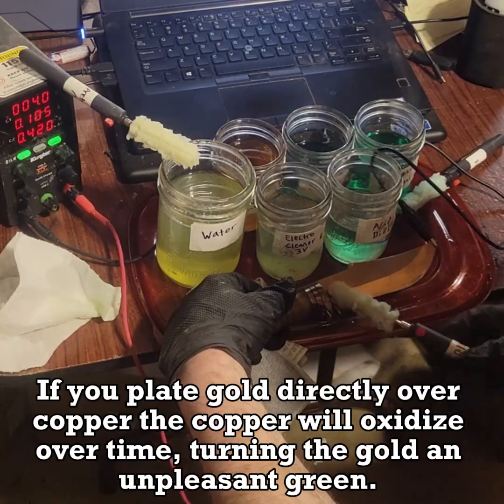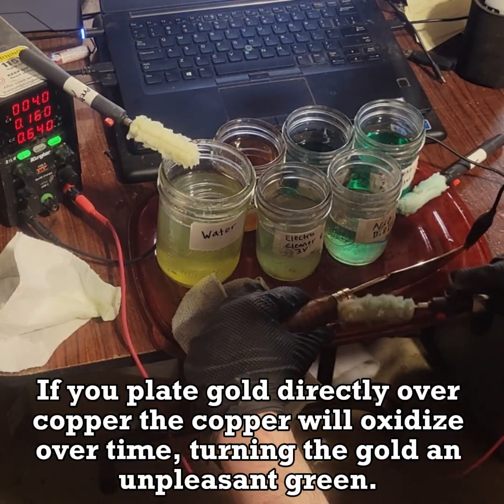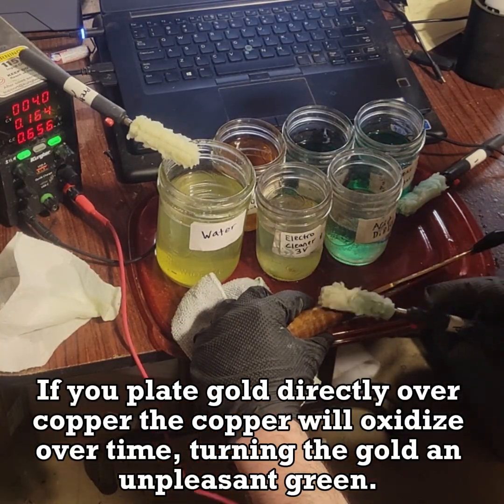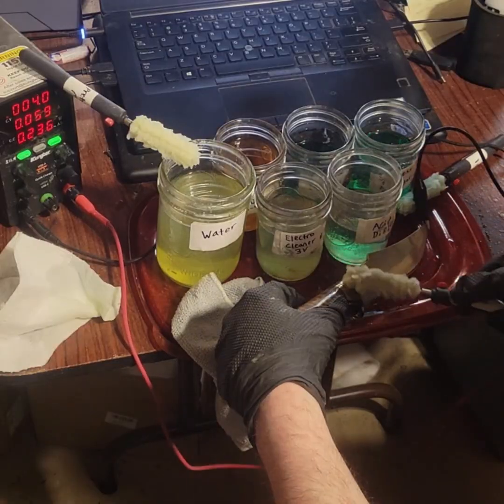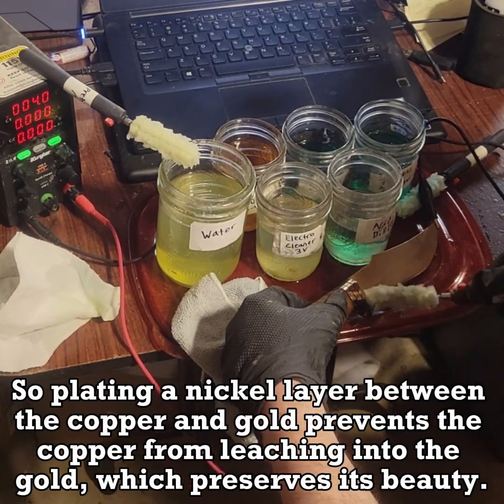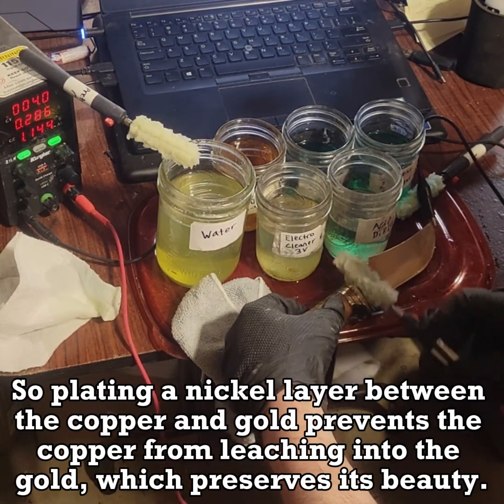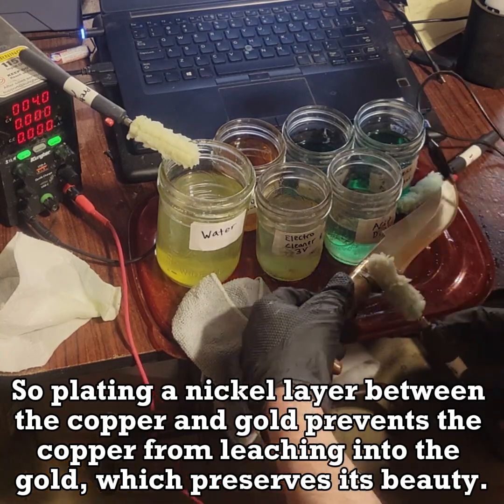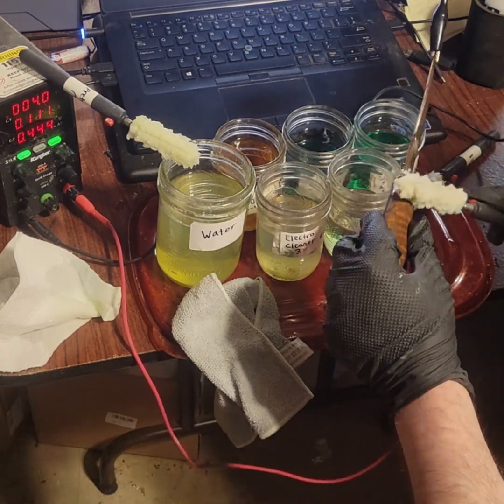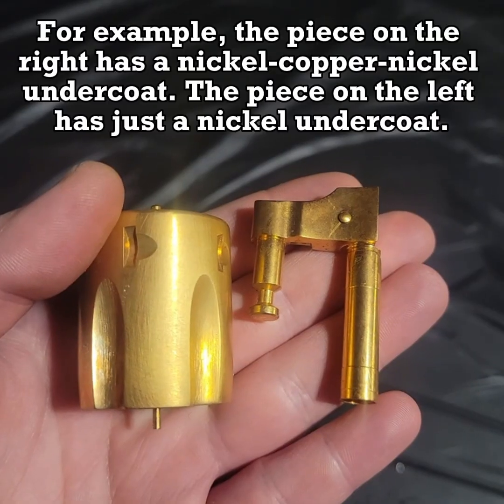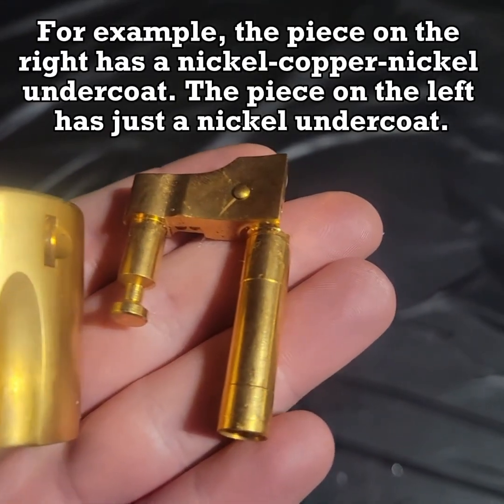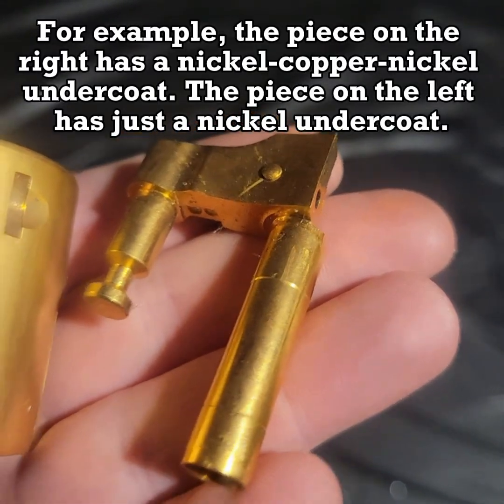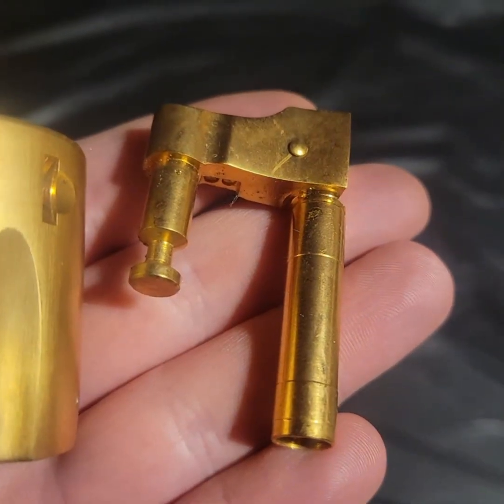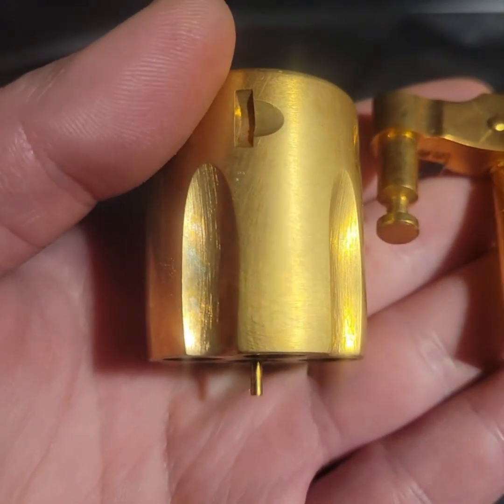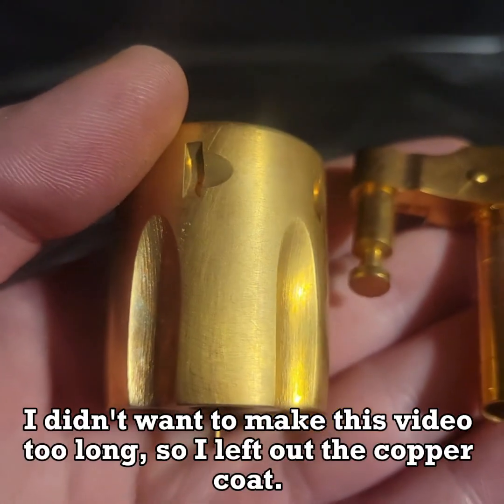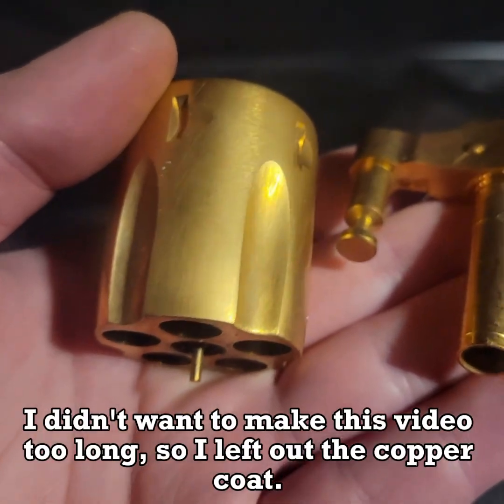If you plate gold directly over copper, the copper will oxidize over time, turning the gold an unpleasant green. So plating a nickel layer between the copper and gold prevents the copper from leaching into the gold, which preserves its beauty. For example, the piece on the right has a nickel-copper-nickel undercoat. The piece on the left has just a nickel undercoat. I didn't want to make this video too long, so I left out the copper coat.